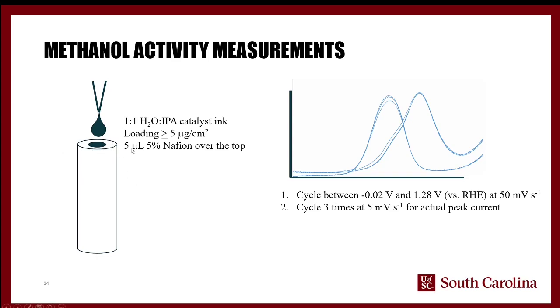And then we use a Nafion solution. Nafion is just an ionomer solution that allows some particles, or some molecules, to travel through it. And it acts in this case as a binder. It's just there to hold the catalyst on. So we put a very, very thin layer on, and it's thin enough that it does not affect the activity significantly.